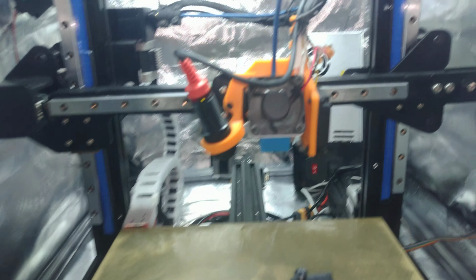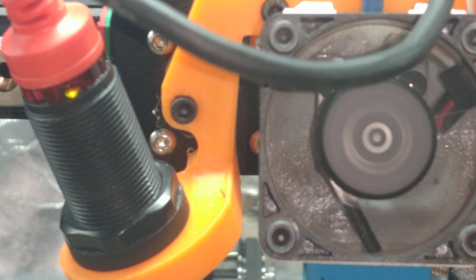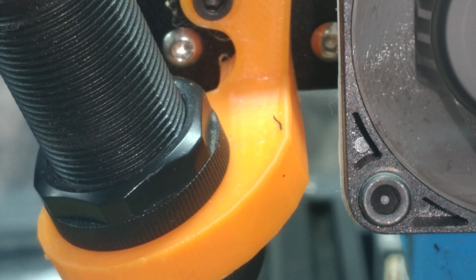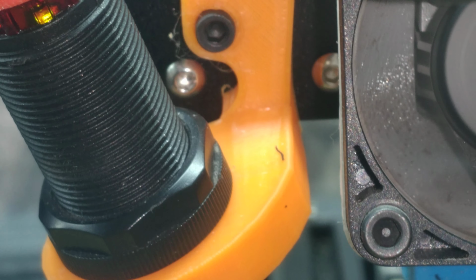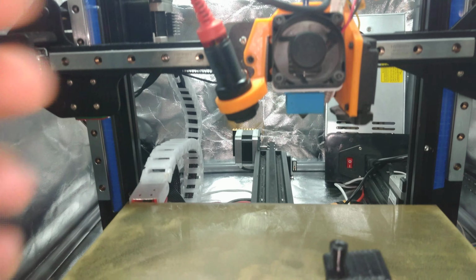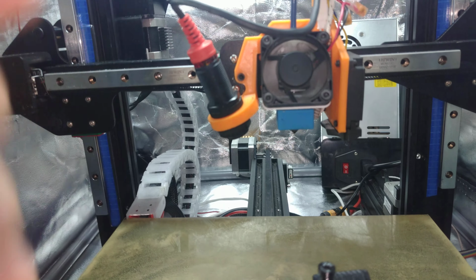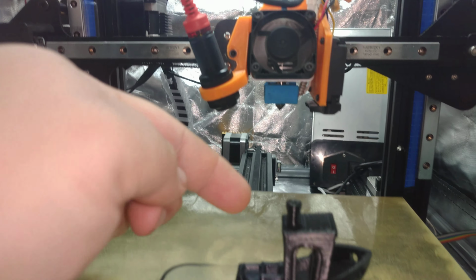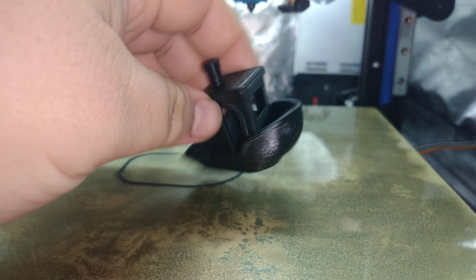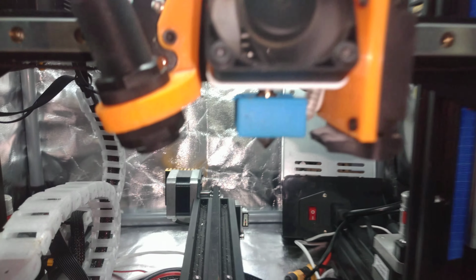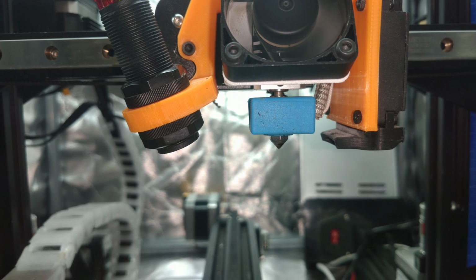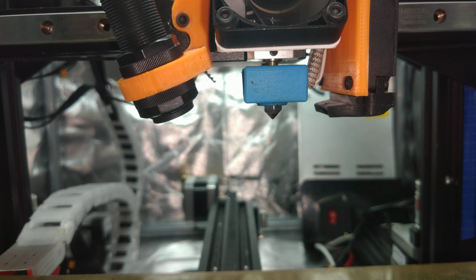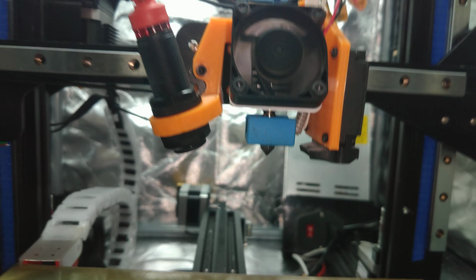That's where PLA has a problem, because that is well above that glass transition temperature of PLA. And as you can see, it started to warp, kind of melting a little bit. Now, I paused the print and had to move my ABL further up, because if I didn't, that ABL probe would be hitting the stuff that it's printing, or the stuff that's printing right next to it as it prints. As you can see, it ain't much higher than the nozzle. In fact, it might even be lower than the nozzle at this point.